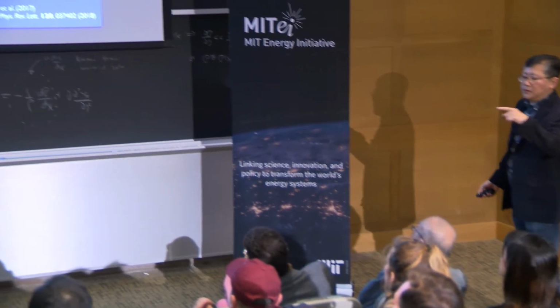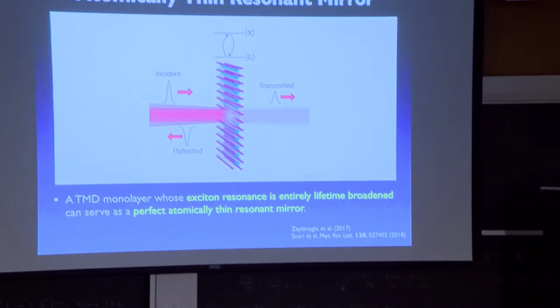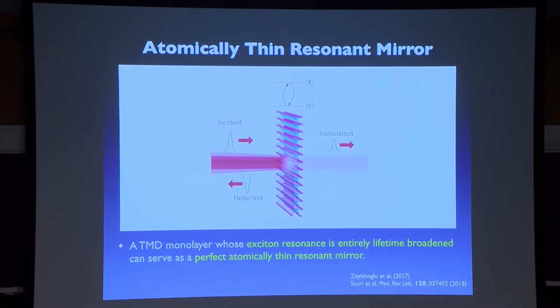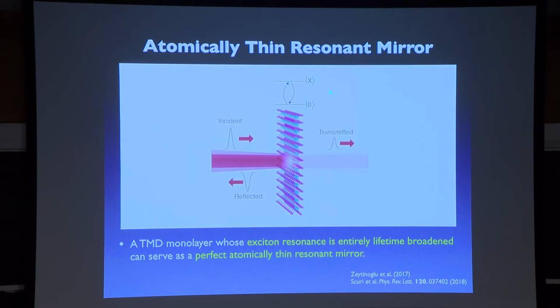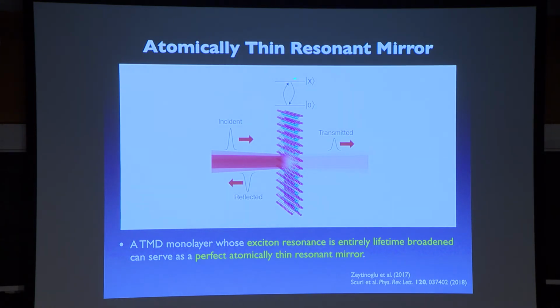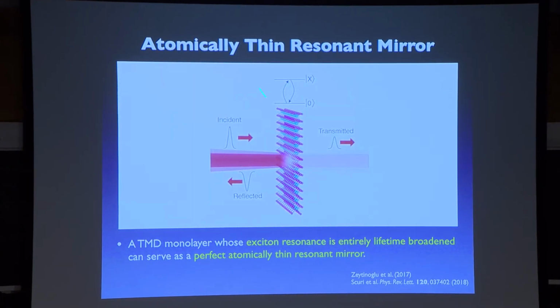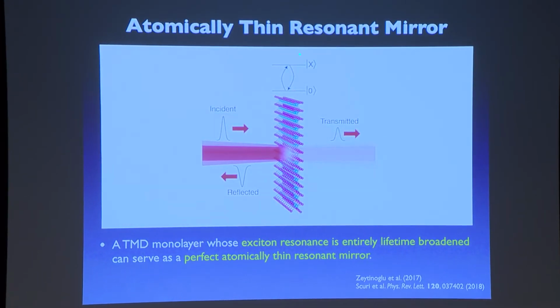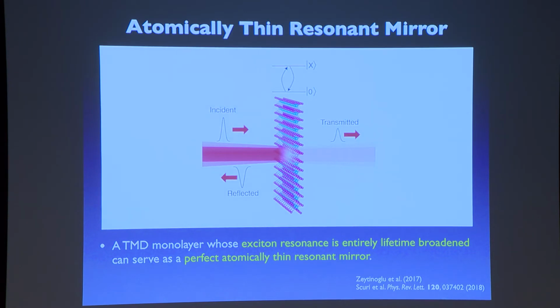But that does not mean that you cannot make a mirror thinner than these limits. At least for a resonant mirror, essentially a mirror for one particular color, you can make it arbitrarily thin. You can make it atomically thin. It works as follows. Let's say that you have a perfect semiconductor which can hold an electron-hole pair known as an exciton. And then let's say that you shine laser light so that you can excite this exciton, which will then relax back to the ground state. During that optical cycle, it turns out that for quantum mechanical reasons, the light that this exciton emits acquires a pi phase shift. Basically, it destructively interferes with the transmitted laser light and constructively interferes with the reflected light. So if you have a perfect semiconductor which can hold a perfect exciton which is entirely lifetime broadened and nothing else, then this atomically thin sheet should act as a perfect mirror for that particular color.